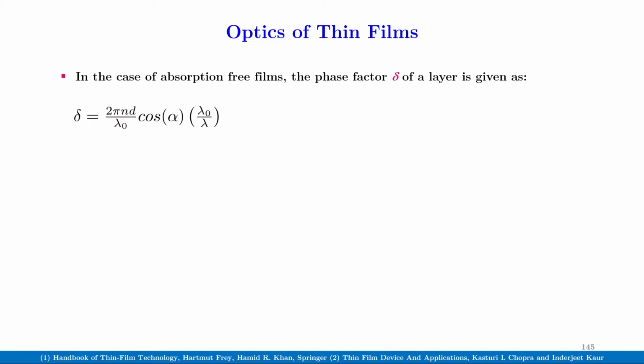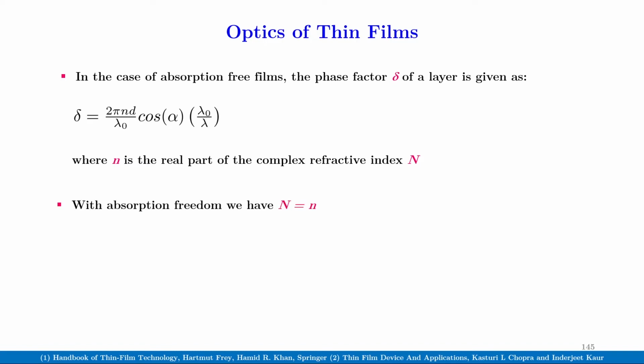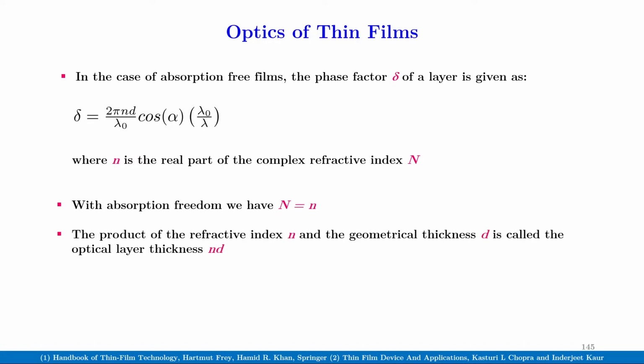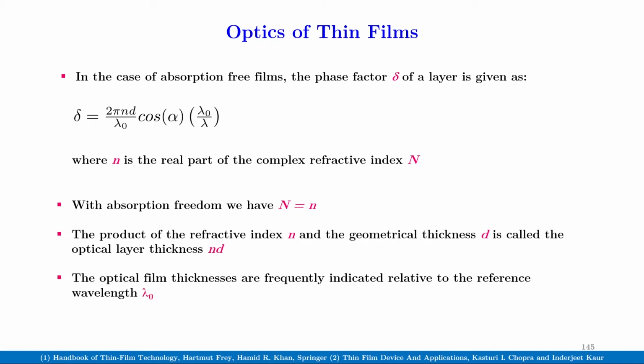In the case of absorption-free films, the phase factor δ of a layer is given as δ equals 2π n d over λ0 cos α times λ0 divided by λ, where n is the real part of the complex refractive index. With absorption freedom, we have N equal to small n. The product of the refractive index n and the geometrical thickness d is called the optical layer thickness nd. The optical film thicknesses are frequently indicated relative to the reference wavelength λ0. That is the reason why we have inserted a λ0 in the above equation for the phase factor δ.